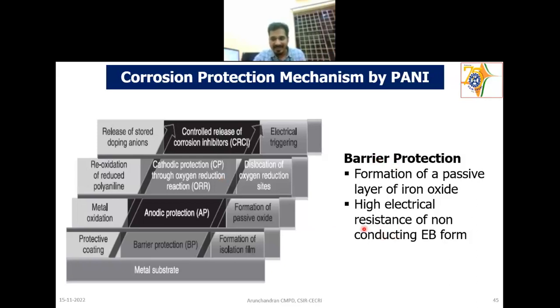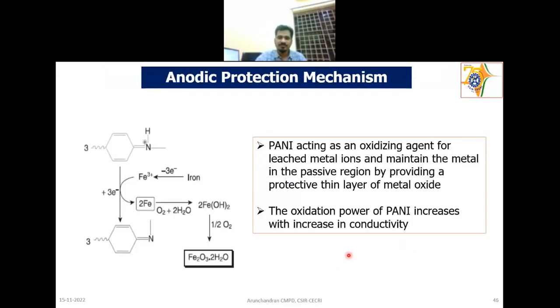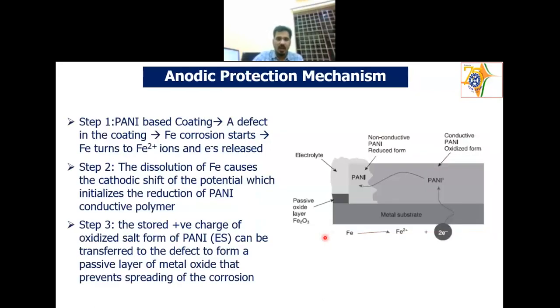That is especially the non-conducting EB form, due to its high electrical resistance, that film can act as a physical barrier between the metal and the surroundings. The anodic protection mechanism is the Pani acting as an oxidizing agent for leached metal ions and maintaining the metal in the passive region by providing a protective thin layer of metal oxide. The oxidation power of Pani increases with increase in conductivity. This we will see how.